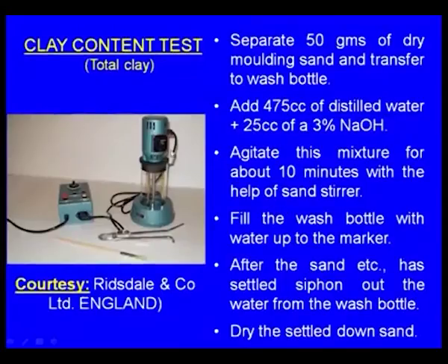This is the sand stirrer. Next, fill the wash bottle with water up to the marker. After the sand has settled, siphon out the water from the wash bottle. Remember, we have mixed the sodium hydroxide. What does this sodium hydroxide do? It separates the clay particles from the sand grains and ensures that the clay floats and the sand settles down.